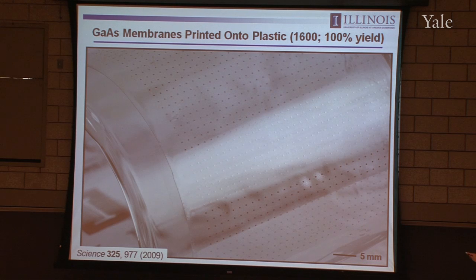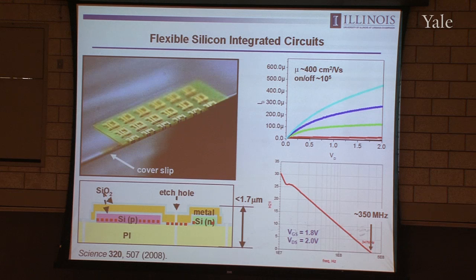By virtue of the fact that the nanomembranes are sticky, they stay bonded to the plastic. They're flexible and floppy, so they can follow the curvature of the plastic in its bent state. And that provides a really exceptionally good starting point for making high-quality electronics, wafer-quality electronics, on a bendable sheet of plastic. I won't go into all the details of how you go about doing that. I'll just make the argument that you have very high-quality semiconductor material on plastic. You can wire it up to make circuits and leave it at that. And you can make circuits that are extremely flexible.